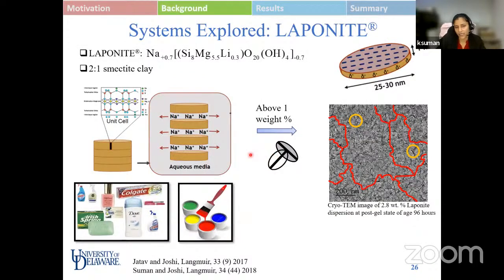So firstly, we select a good model system for this study, which is a suspension of laponite particles. Laponite is a synthetic clay-like particle with the unit cell formula given over here. These are disc-shaped particles around 25 to 30 nanometers in diameter and 1 nanometer in thickness. On dispersion in water, water enters the interlayer gallery, and the sodium ion dissociates into the water, rendering the face a negative charge, whereas the edges acquire a positive charge.